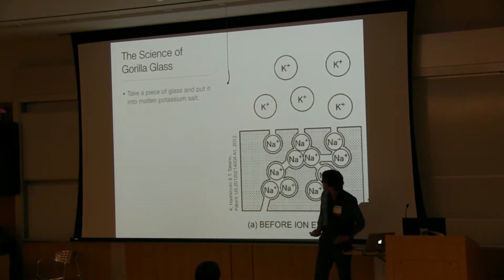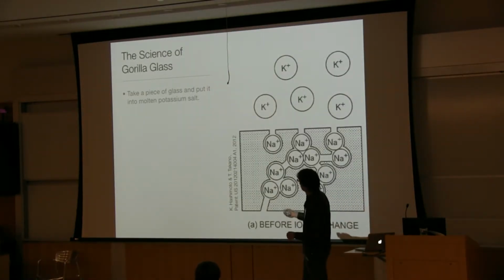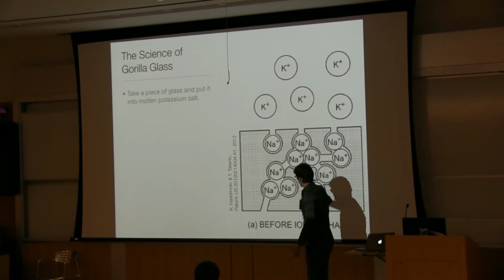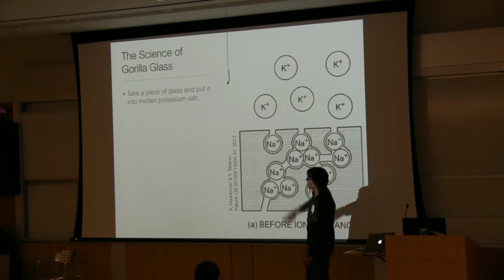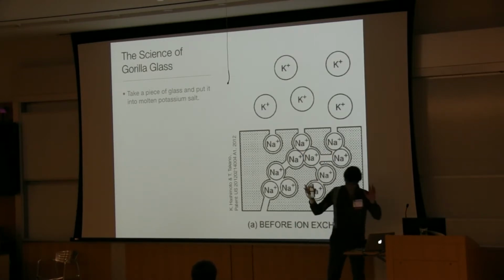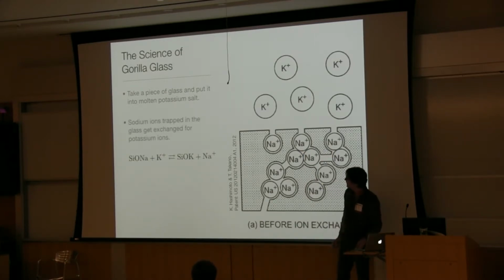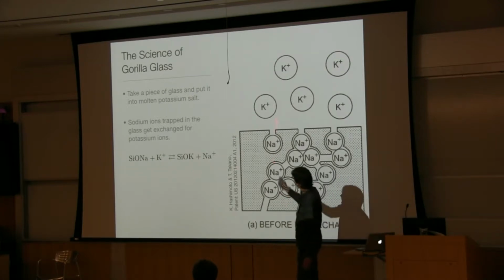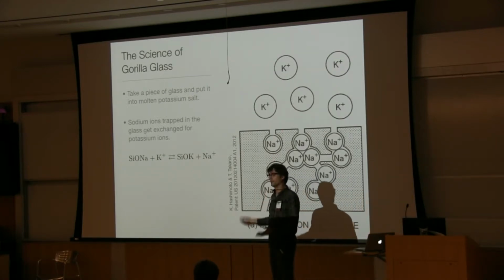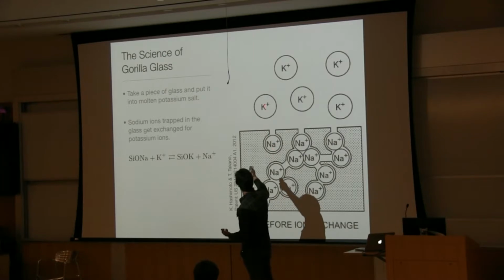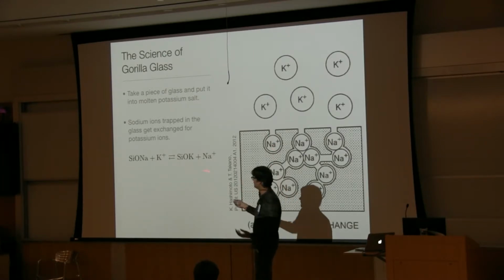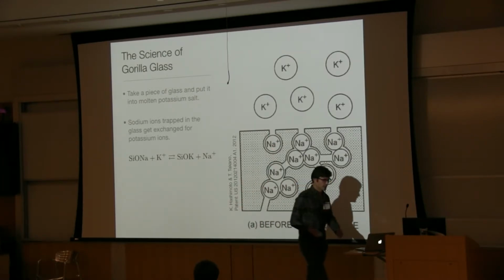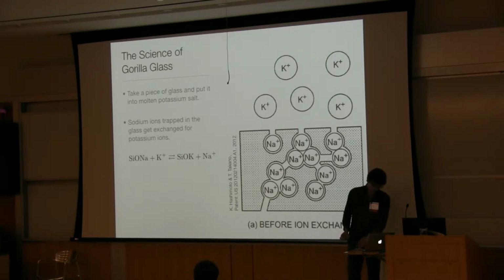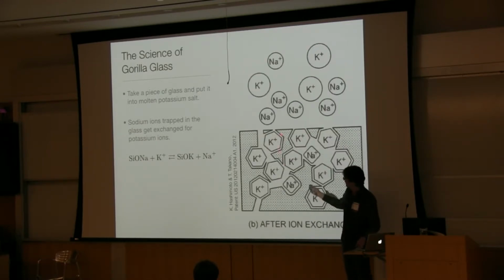So Gorilla Glass works the following way. You take a piece of glass that has little sodium ions inside of it, and you jam the glass into molten potassium salt. So just molten potassium. And when you do that, the sodium and the potassium ions can exchange with one another. There's no reason that the sodium has to live in the glass. Some of them diffuse out, some of the potassium diffuse in, and you have a reaction that eventually goes to equilibrium.